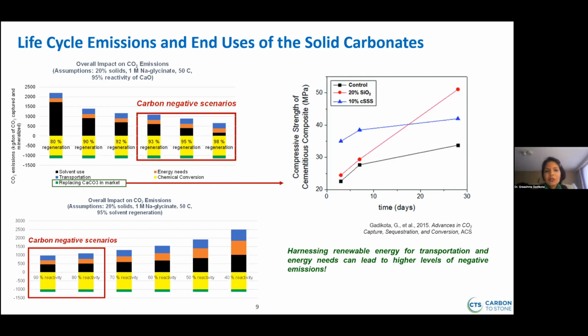So some of the most effective ways to actually achieve higher levels of carbon removal are to co-locate our facility with the alkaline resource itself, so we avoid the emissions associated with transportation. Another strategy is to increase the solvent recovery efficiency. Another strategy is to actually replace, I would say more specifically, natural calcium carbonate with the calcium carbonate that we are synthesizing.